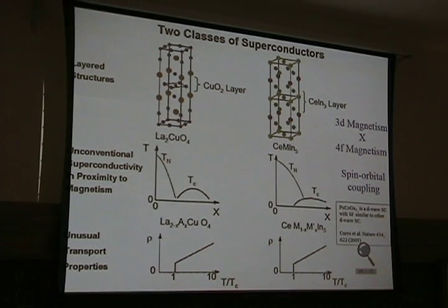just showing the dynamics of the spin measured by NMR. They have linear resistivity in the normal state in both cases, for the cuprates and for the 115. That's experimental fact. Well, how about the difference? I just said one of them, that the charge should play an important role in the case of the high TC, because you are driving an insulator into a metal when you are doping your material. Here we have a metal all the time.